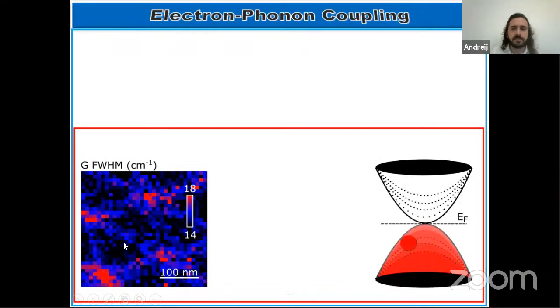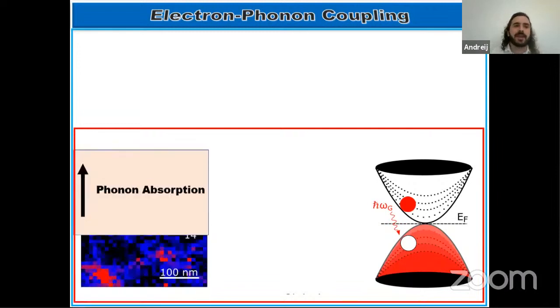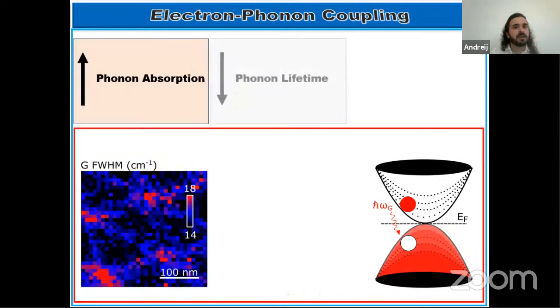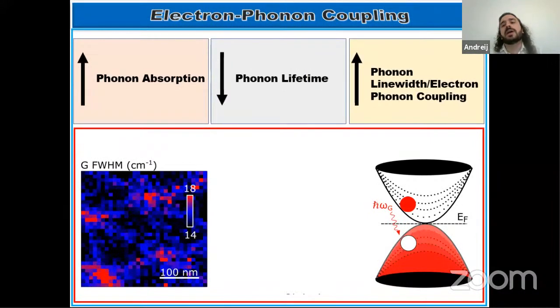To understand this, we need to look at the electronic structure close to the Fermi level, where G phonons can be absorbed generating electron-hole pairs, and we can say that the G phonon is coupling to the electron. And the larger the phonon absorption, the smaller the phonon lifetime. And from the uncertainty relation from Heisenberg, we can tell that the phonon linewidth increases.